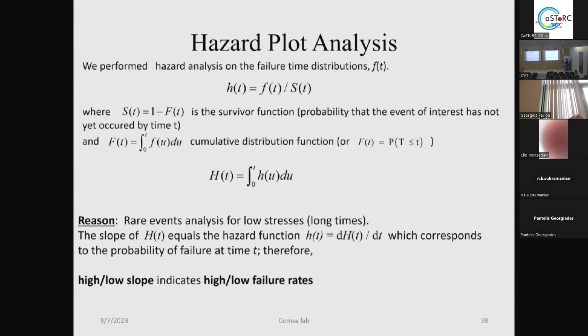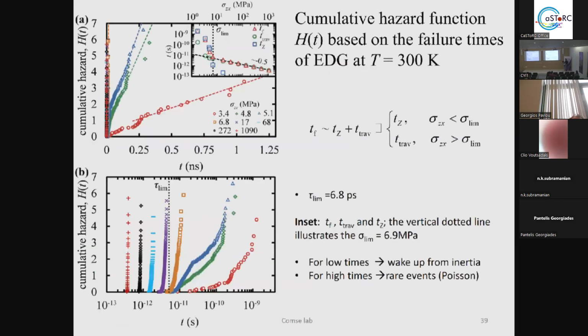That's why we agreed to explore the system and the phenomena with the help of hazard plot analysis, taking into account the survival functions and the cumulative hazard plots, from which someone could estimate the possibility of a failure through the rate, through the slope of the system. And so you can see here that depending on the slope, you have a different type of failure.